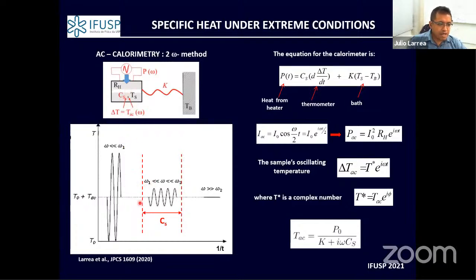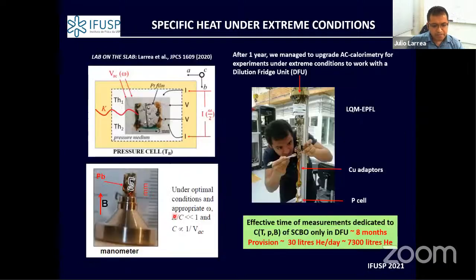However, if you apply a very small frequency, the heat dissipates more over the whole system, even touching the pressure cell, and therefore your signal will have more contribution from the addenda and the pressure cell, so that you will not see the signal of the specific heat. Therefore, a compromise between these two different frequency limits will set the good criterion to obtain the specific heat of your sample.